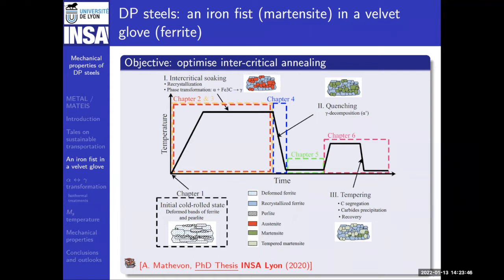The first is the study of what's happening during this intercritical soaking. In fact, when you heat, it's fully ferritic and then turns into a mixture of ferrite and austenite, and we would like to have a model for the kinetics of formation of austenite. Then we would like to have another model to predict the martensitic start temperature, in order to know at which temperature this transition occurs and solute atoms cannot diffuse anymore in the matrix. And eventually, we would like to know what's happening during tempering of these martensites.